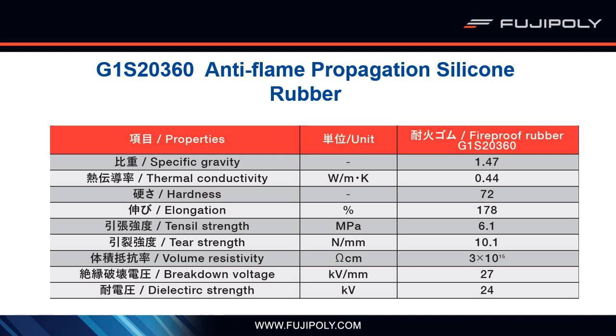So the G1S20360 being a silicone, it's going to have a lot of the typical properties that you would see with a silicone rubber. Specific gravity is about 1.47, which is in line with most silicones, at least silicones that aren't loaded with things like electrical or thermally conductive fillers. In this case, the thermal conductivity of this material is about 0.44, so not a high conductivity material. Hardness is a 72. The elongation on this material is about 178%, so it is still very much an elastomer. Tensile strength 6.1 megapascals, tear strength about 10.1. Volume resistivity, it is an insulating material, so 3 times 10 to the 15th ohm centimeter. Good breakdown voltage, comes in at 27 kilovolts per millimeter, and a dielectric strength of 24 kilovolts.